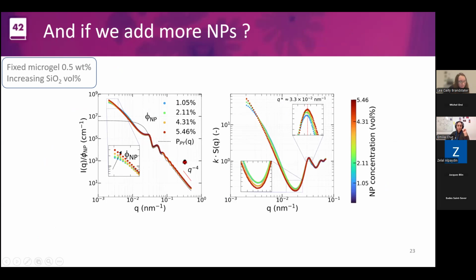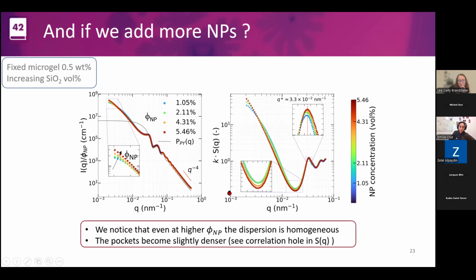Now you're familiar with this kind of representation. You know that when you see this, you're seeing a pocket within this microgel, and you see that the pocket becomes a little bit higher in intensity, so meaning that it becomes a bit bigger, perhaps. You can also look at the structure factor and try to understand this, like I was telling you, this correlation hole that tells you about the population of particles inside the pocket, which is going deeper and deeper for higher nanoparticle content. So that is already telling you that the pocket is more populated, but pretty much it's a homogeneous structure that exists within the soft glass. There's no dramatic changes, and they become slightly denser.